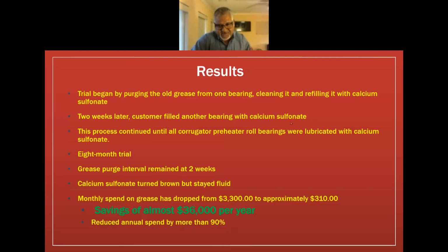When I went there to demonstrate the purging process, that was just one of the 8 rolls on these corrugators. So every 2 weeks, they would purge and fill another set of roll bearings with the calcium sulfonate grease while the machines were operating. This process continued until all the corrugators were full of calcium sulfonate grease. It's about an 8-month trial. The grease purge interval remained at 2 weeks.